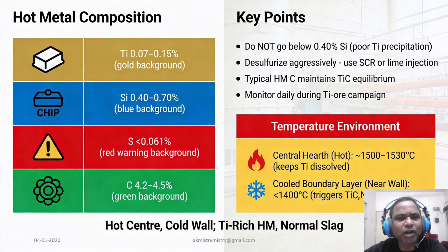Hot center and cold wall are the best combination to segregate nuclei of TiCN on the furnace wall and even in the corners and bottoms of the carbon brick. The central hearth should be between 1500 and 1530 degrees centigrade to keep the titanium dissolved, and for this operators are requested to keep focus on the apparent central point temperature very well during the execution of this project. However, near the wall the temperature must be under 1400 degrees centigrade to trigger the precipitation of the protective TiCN layer. During this operation each member of the blast furnace team must be focused on the cooling system of the side wall.